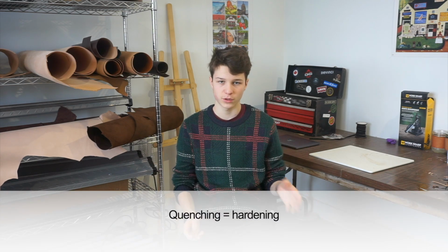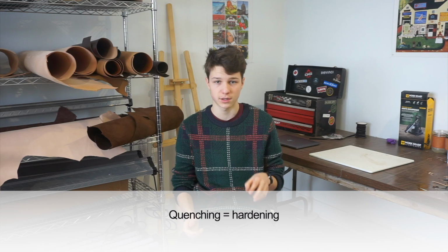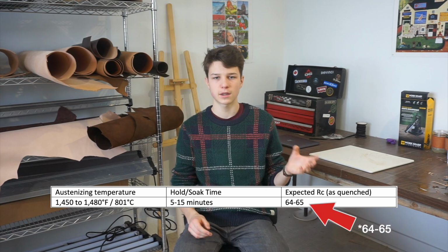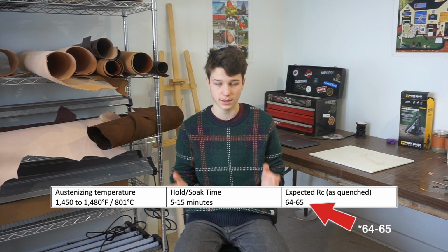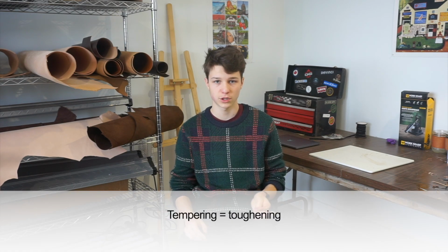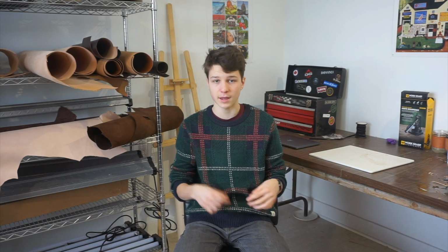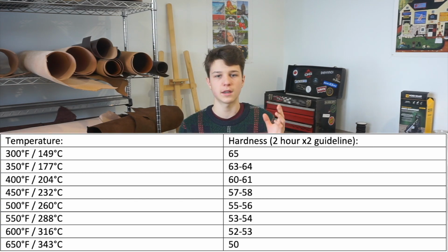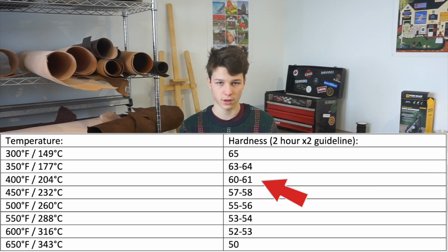So for 1084 steel, the ideal HRC, or hardness level, of the steel after quenching, which is the second step in the heat treating process, which is the process of making the blade hard, it should be ideally 64 to 65 HRC. Now after tempering, which is the third step in the heat treating process, which is taking the very hard but now brittle blade and tempering it to make it tougher, the ideal HRC then, after the whole heat treating process is complete, should be ideally 60 to 61 HRC.